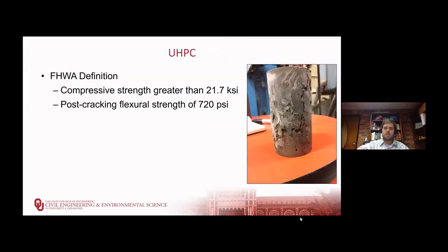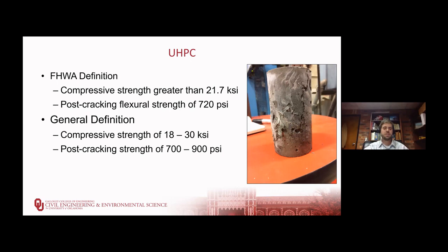So the question is, what is UHPC, or ultra-high performance concrete? It's a cementitious composite with steel fibers included in it. FHWA defines UHPC as having a compressive strength greater than 21.7 KSI and having a post-cracking flexural strength greater than 720 PSI. But we can extend that to a more general definition as a cementitious composite with a compressive strength between 18 and 30 KSI, and still having that high post-cracking strength of 700 to 900 PSI.